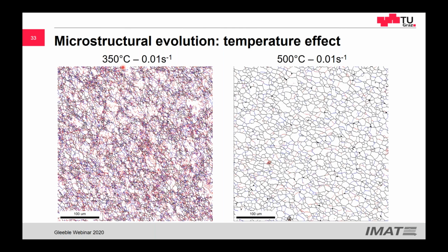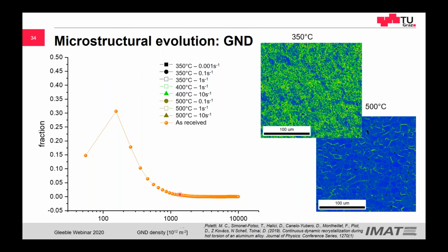The lower the temperature and the higher the strain rate, the smaller this substructure is. And it takes also longer for the total recrystallization, as you can see here. The black lines, this is almost 100% recrystallized, very nice. And here we still have a lot of substructure. So we also did some measurements of the geometrically necessary dislocations. This gives an idea of the percentage of recrystallization, more or less, if I can put it in these words.